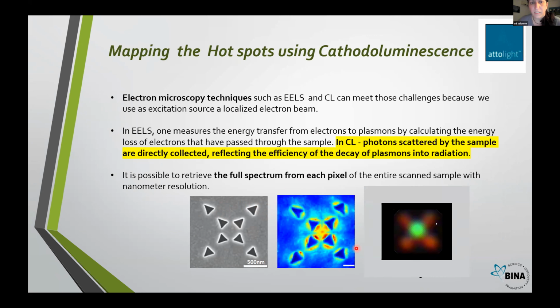From cathodoluminescence, it's possible to retrieve the full spectrum from each pixel of the scanning, as you can see from this example. This is the optical image of this structure, a cross structure, where you can beautifully see that we have a hotspot located between the cavities, and the high electromagnetic field is concentrated between the cavities here. You can also see the antinodes, much like molecular orbitals.